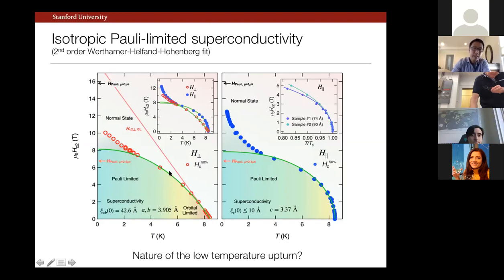And now we're taking the so-called WHH fit. So this is an extended theory taking both orbital and paramagnetic effects into account in the full theory. And this is a second order fit to this WHH fit. Okay. Now, this is the in-plane direction. Again, we put the magnetic field in the plane. This is the square root that I told you about. As I previously discussed in some detail, it doesn't scale with the geometry, nor does it give you a sensible number for the thickness. And then it varies in this rather unusual way.